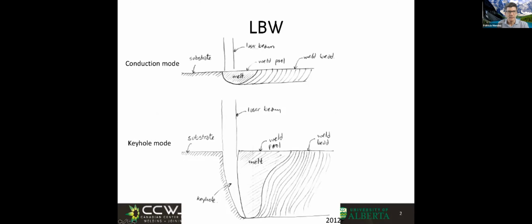In this case, in which the beam is melting locally, actually, there is very little difference with TIG at relatively low currents. If TIG was running at higher currents, then the plasma jet can cause a deformation in the weld pool and can have the consequences of humping and other defects.